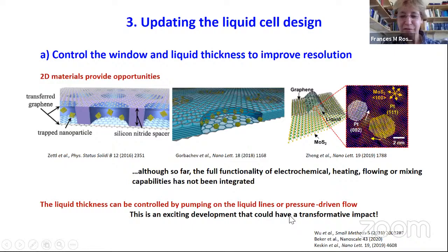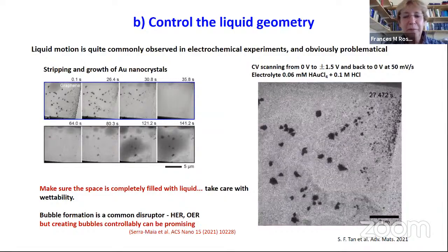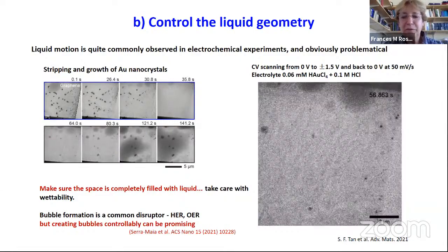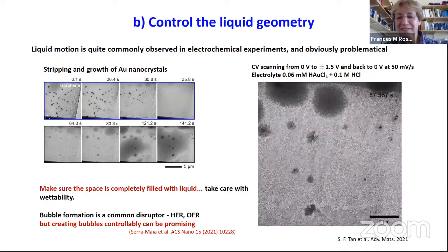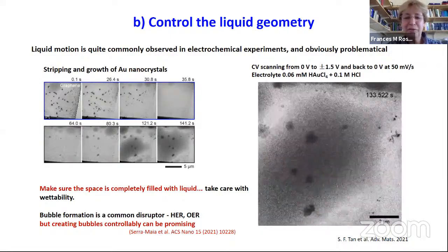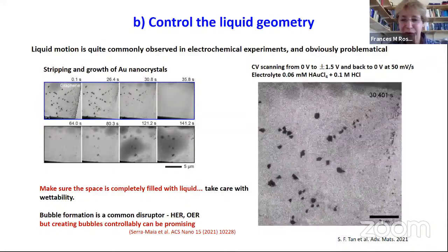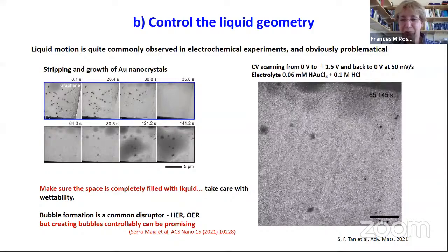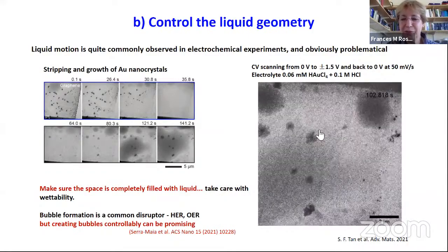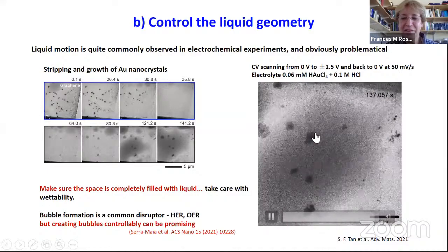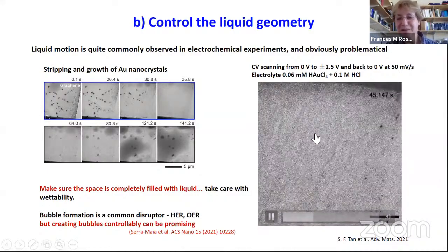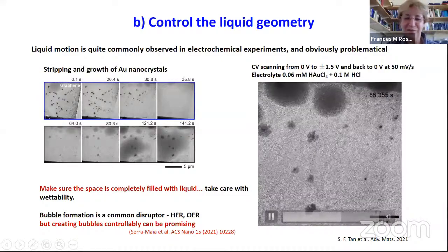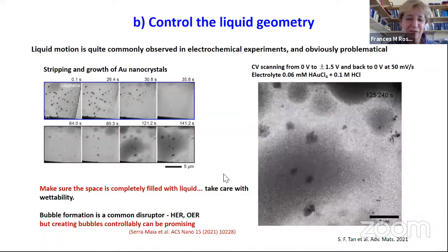I think this will have a transformative impact on future liquid cell microscopy, just the ability to control where the liquid is and how thick it is. So here's an example of what you might call a typical complicated, hard to interpret experiment. During the electrochemical process, which here is growth of gold particles, you can see that the liquid is jumping around all over the place. And this is generally bad, because we like to know where our liquid is for the electrochemical reaction.